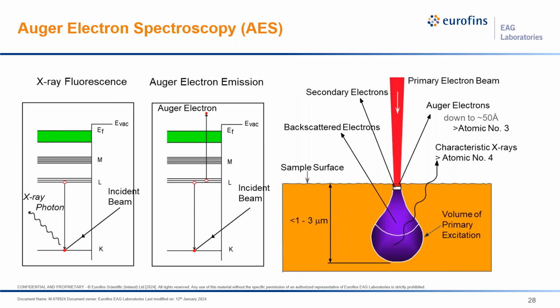Slightly more detail for Auger. It's a complementary technique to EDS. So we have the incident beam removes a core electron. In the EDS, we see the secondary, the photon emission, detect and monitor that. For Auger, it actually involves the emission of a second electron, the Auger electron here. So that core hole is filled, and we have the ejection. So that's a 3-electron process.